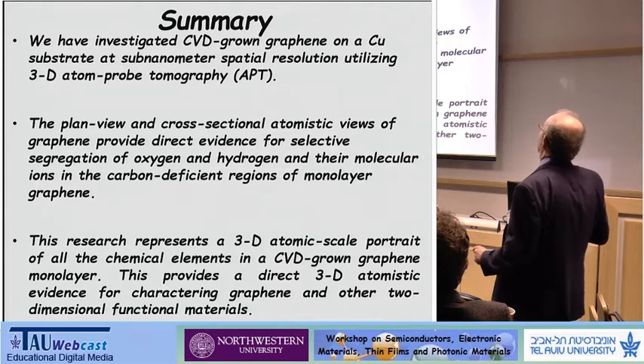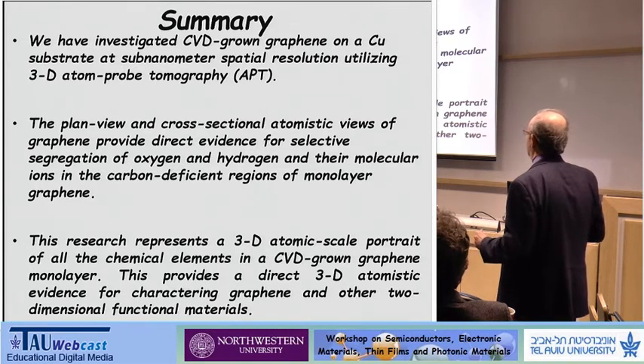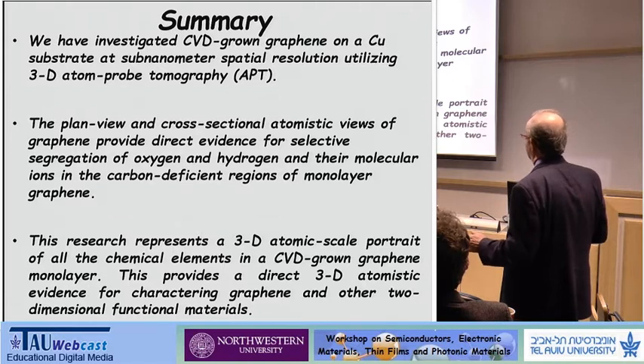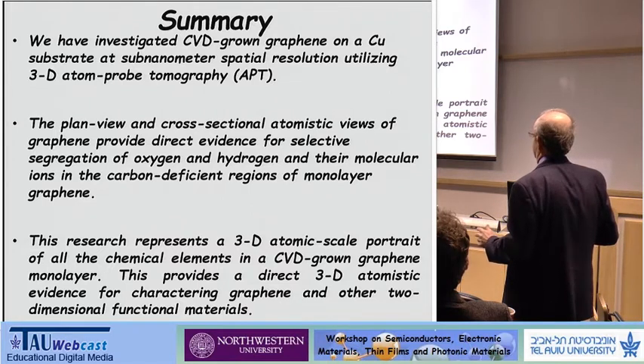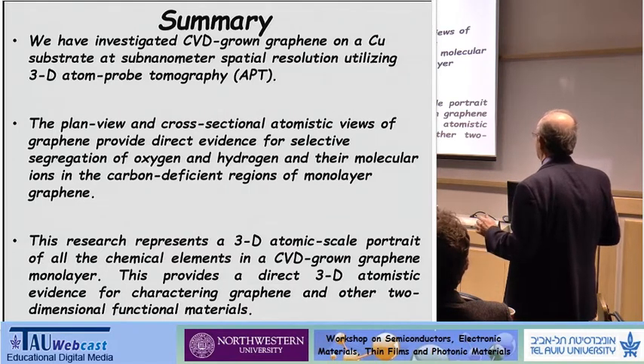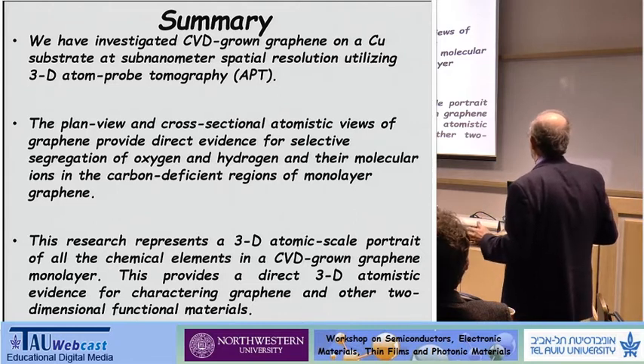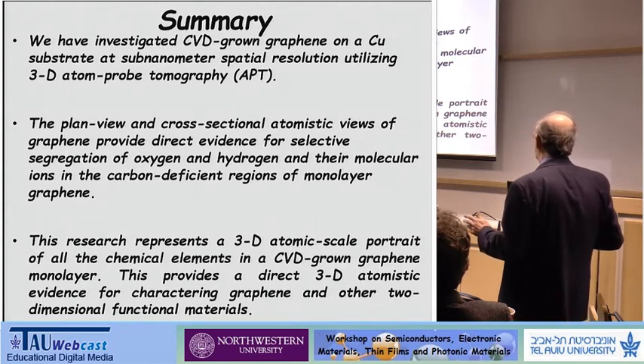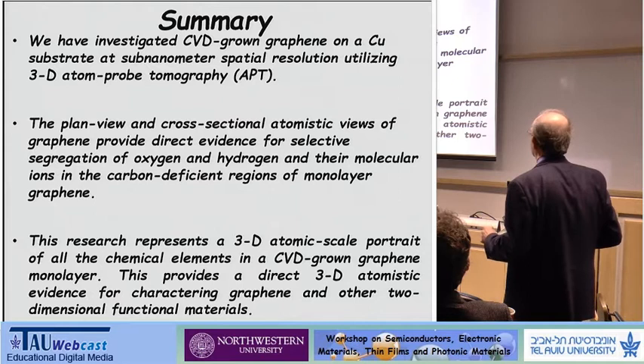Okay, so in summary, what we did is we looked at CVD-grown graphene on a copper substrate. We analyzed it with atom probe tomography, and we're able to get both plan view and cross-sectional views. And we can see how the oxygen and hydrogen are distributed between the regions that have the right carbon density and regions that are carbon deficient. And we're looking at monolayer graphene. And so what we have is an atomic scale portrait of all the chemical elements that are involved. And I think, and I hope, that this atomistic evidence for characterizing graphene can be extended to other two-dimensional functional materials. So that's the graphene part.